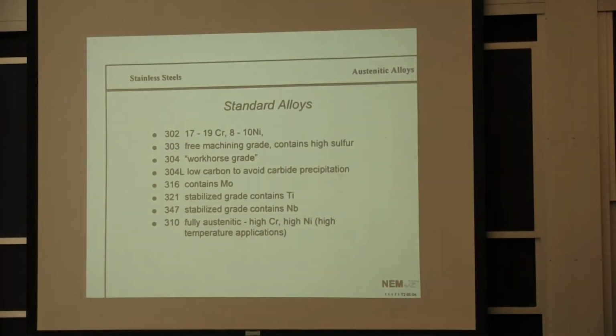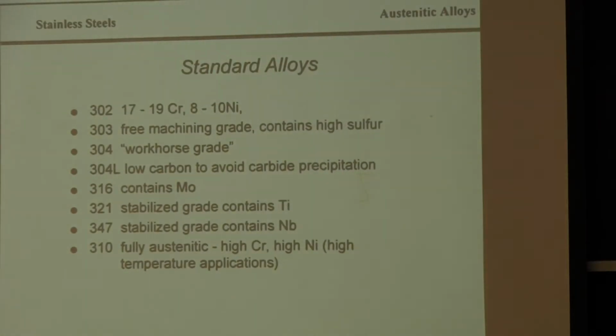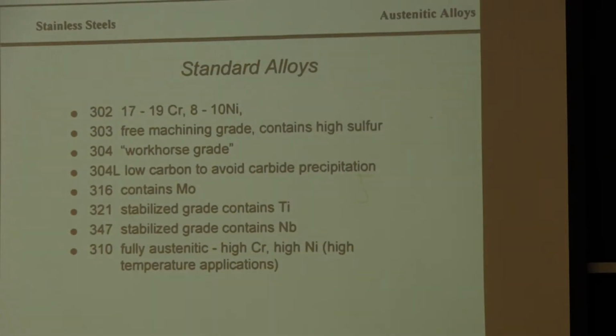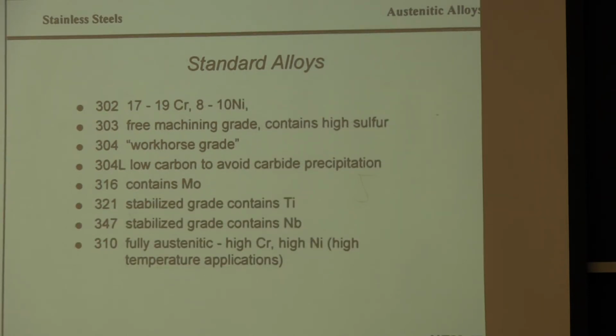Another one that I'll mention is both the 321 and the 347. They're what's called stabilized grades. We're going to talk a little bit about intergranular corrosion of stainless steels, and the titanium and the niobium that are in those grades will tie up some of the chromium carbides that would normally be formed, and they'll prevent some corrosion, what's called intergranular corrosion.